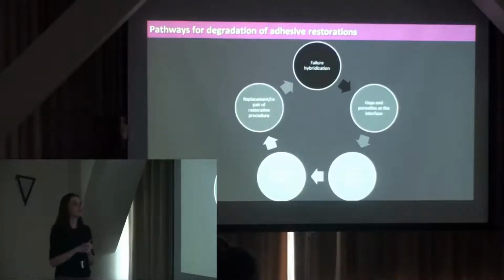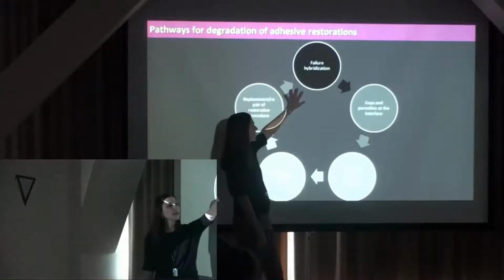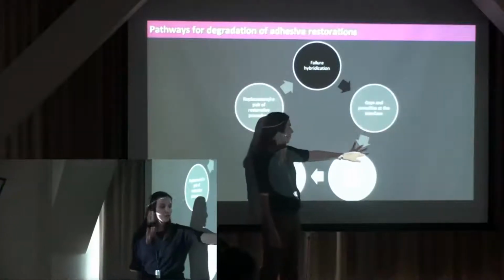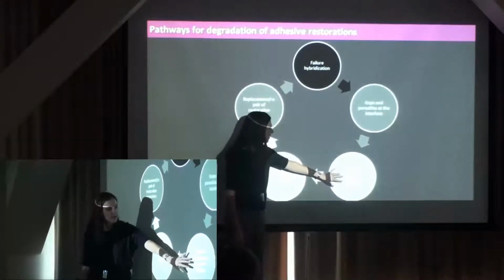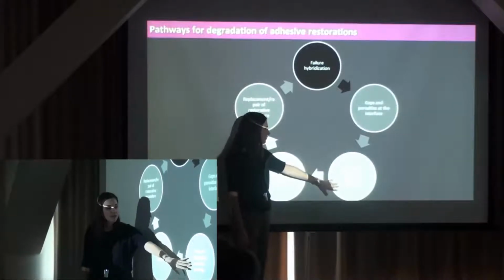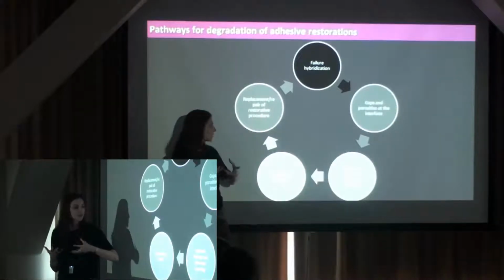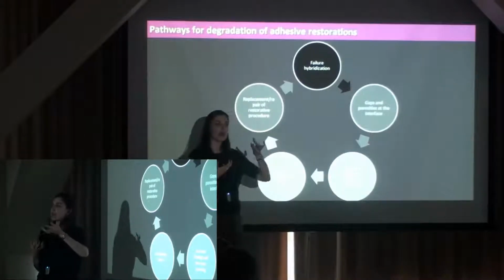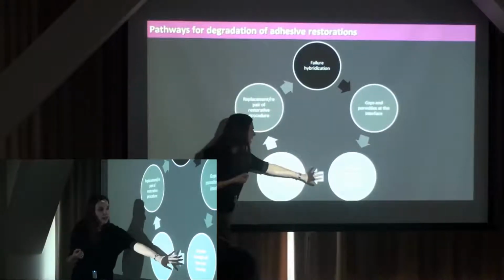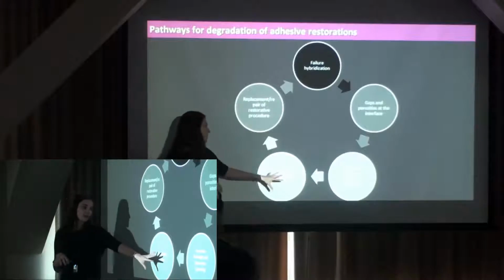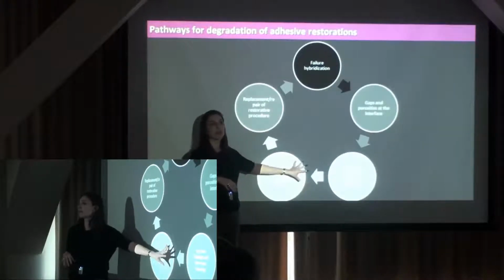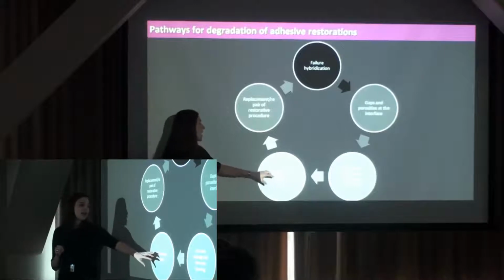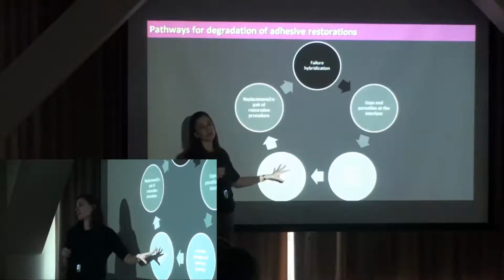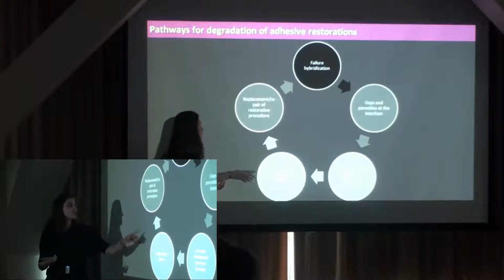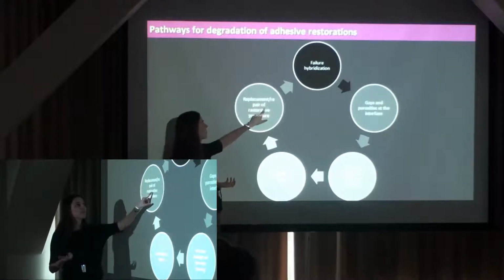So basically what we have nowadays is this. If we don't hybridize appropriately, you have these gaps and porosities. Over time it increases the leakage, so you have increased porosities. It will decrease the bond strength because you lose that anchorage from the hybrid layer to the dentin. And if you have that porosity, it's a wonderful opportunity for the bugs in the mouth to sit there and start another process of decay around this restoration. Then you go to the dentist, you replace it, and if that's not done right again, it gets to a cycle.